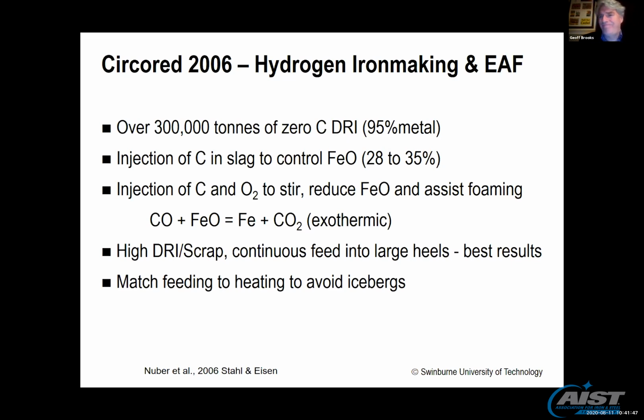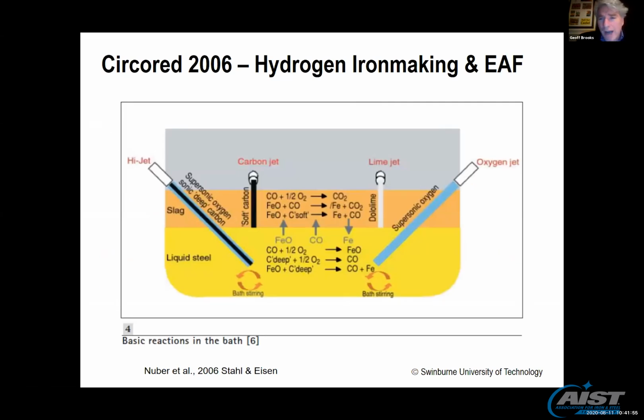So that was the general experience that they reported in that paper. And it makes sense. All those things make sense to me. They have a diagram where they set out the importance of making sure you get some carbon and oxygen deep in the bath so you can stir the bath and help flush out the nitrogen, as we've already been discussing. They also advocate putting carbon into the slag. So you can see straight away your desire to get rid of carbon from the process is compromised by all these requirements to remove nitrogen, foam the slag, etc.